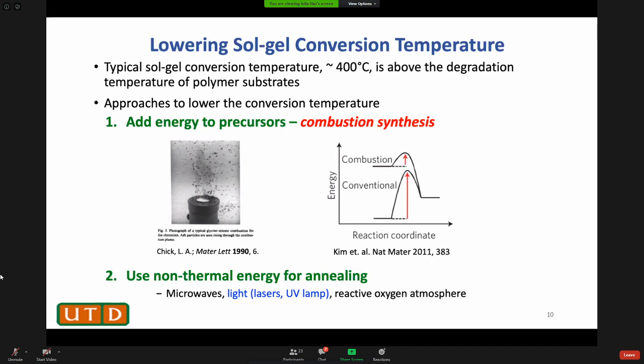Yeah, but X-ray amorphous at least. In X-ray, we didn't see anything. People say nickel oxide would be crystalline, people even publish nickel oxide, but in our thermal anneal and our photonic cure, nothing is crystalline. So maybe it has to do with the precursor.